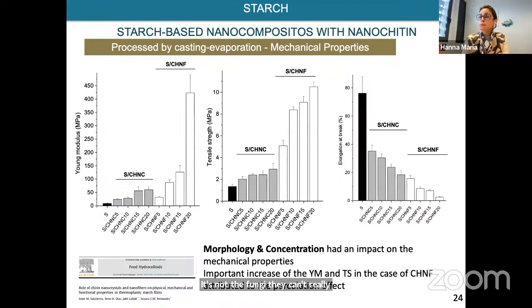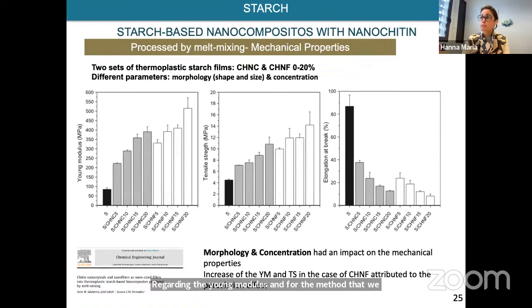Regarding the mechanical properties, as expected, we found that chitin nanofibers, as they are longer, show better mechanical properties regarding the Young's modulus. This was for the method that we used with casting evaporation, but we also found the same kind of properties with the materials that were prepared by melt mixing.